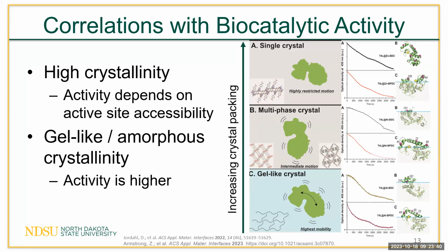It's not going to be exactly the same for every protein in the material. And we found that gel-like or amorphous materials, or even our multi-phase crystals, where there are various crystalline structures in our metal organic material or framework, had higher activity. It didn't matter if the active site was exposed or buried. On the bottom right, if you look at the aluminum BDC and BPDC, the activity is phenomenal compared to, say, the zinc BPDC on the top, even though the active site for the aluminum BDC MOF is likely to be buried within the metal organic framework or just barely poking out for the aluminum BPDC.